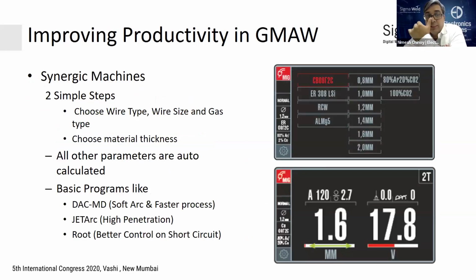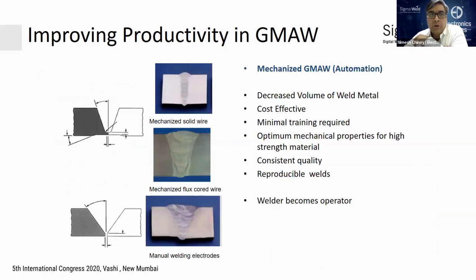Synergic machines have two basic steps. You can choose the material and the wire size and the gas, and it will calculate all the other parameters for you, thereby taking away the skill from the welder and putting it right back into the equipment. You can have basic programs such as soft arc or faster process. We call it DAC-MD in the Pro series that Sigma Weld has. You have jet arc for very high penetration, and you have root for better short circuit control. We'll see a little bit more on that.